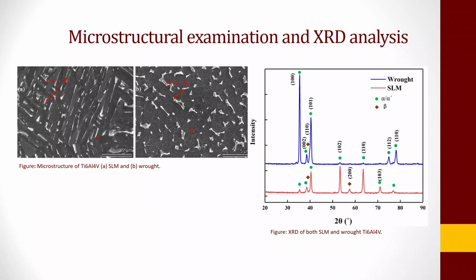So let's first look at the microstructure analysis. These are the micrographs we got using scanning electron microscopy. You could clearly see that in the SLM, or selectively laser melted sample, the beta is more elongated. However, the beta in the wrought samples is more agglomerated instead of more columnar or longer, right?